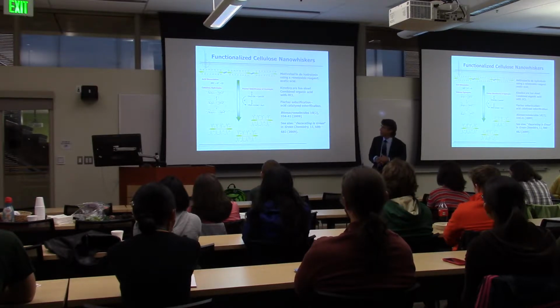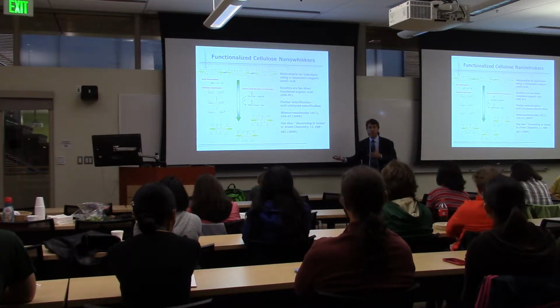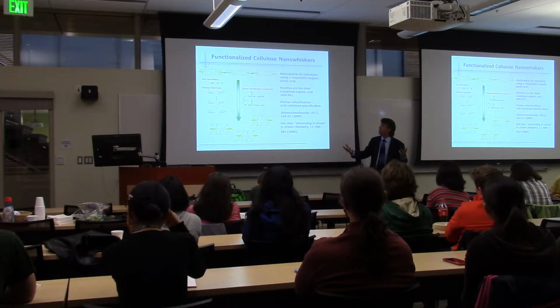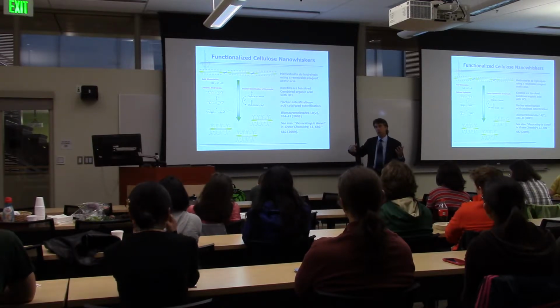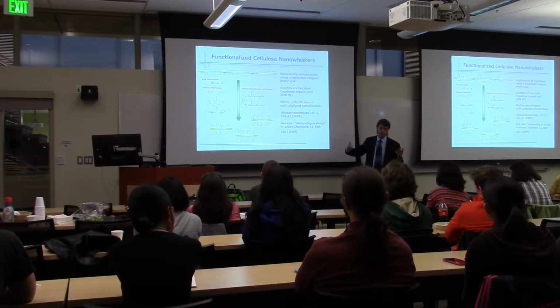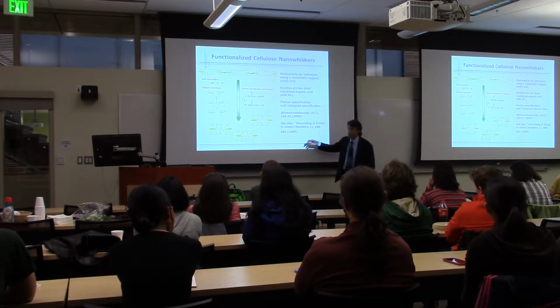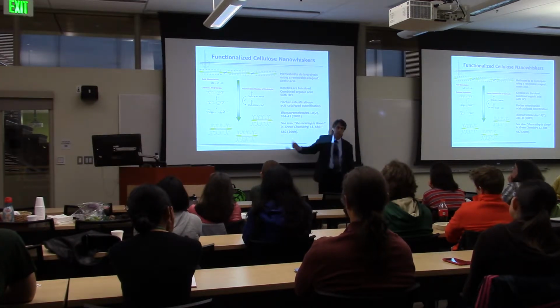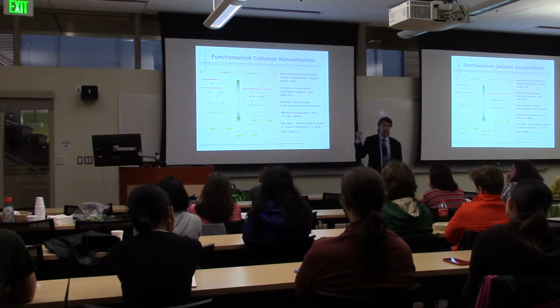And what we got to, through the typical type of research path of going here and going there, was the fact that you could do a one-pot, single-step methodology by combining the hydrochloric acid with an organic acid. And so when you do that, not only do you hydrolyze away the amorphous regions of the cellulose and leave behind the whiskers, but you also do an esterification reaction on the surface, and so you're simultaneously doing the surface decoration. And so here I show that with acetic acid. So we're really just making cellulose acetate in this particular case. But we've done this with all kinds of different acids. So you can do it with butyric acid, although that's kind of stinky stuff.